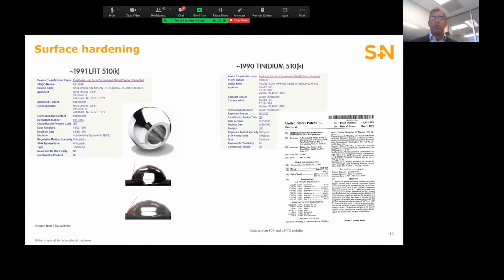Another surface hardened material that was developed is called tinidium. Tinidium utilizes nitrogen as well. However, in this case, the substrate is titanium. While both of the processes differ, one of the limitations that they share is that the depth of hardening is relatively limited. For example, the depth of hardening of tinidium is estimated to be about 0.5 micron.